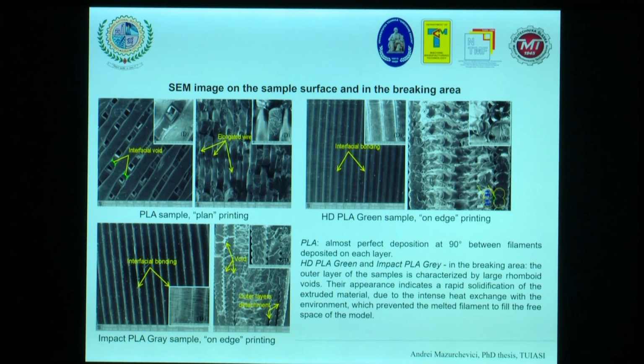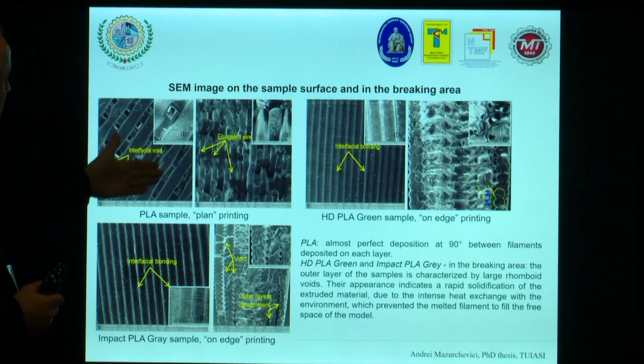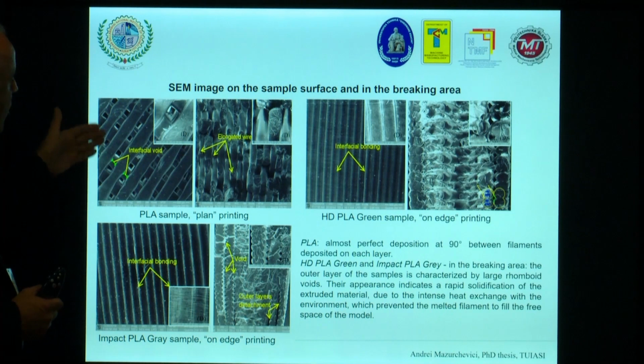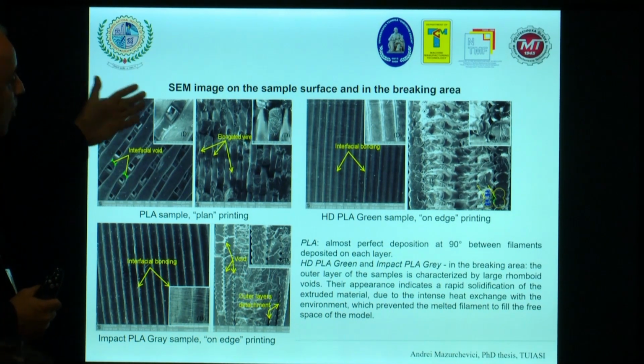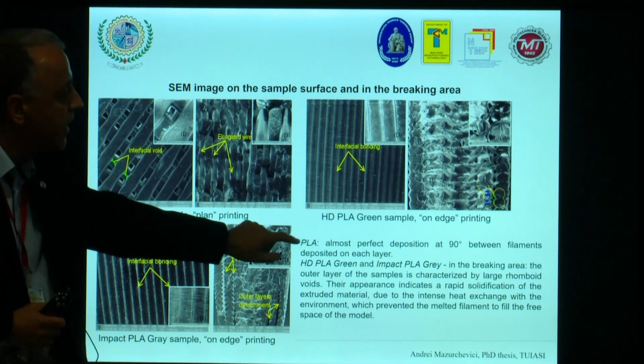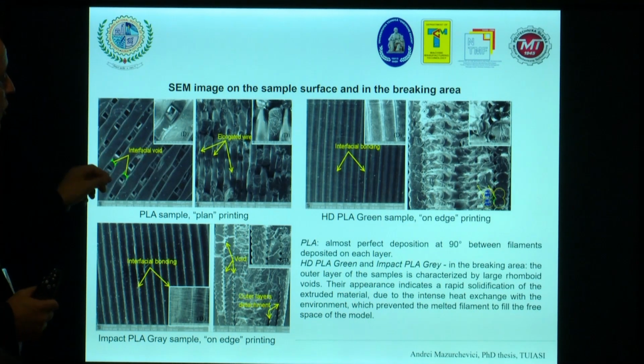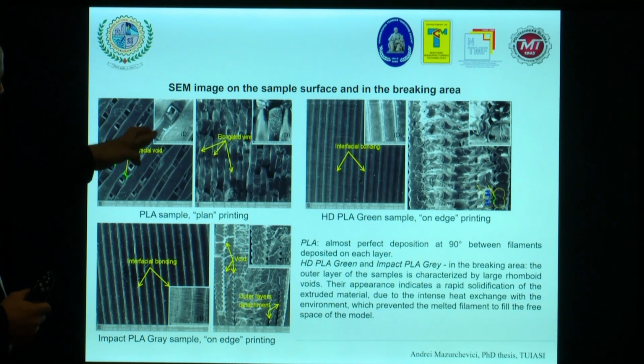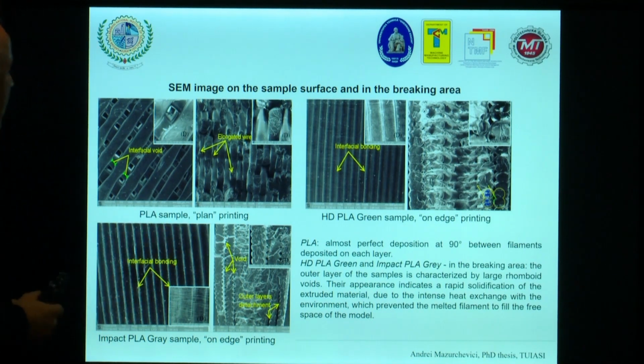SEM image on the sample surface on the breaking area. In case of PLA, you can see that the SEM image is quite good. I mean, almost deposition at 90 degrees between filaments deposition on each layer. You can see, yeah, good layers deposition.